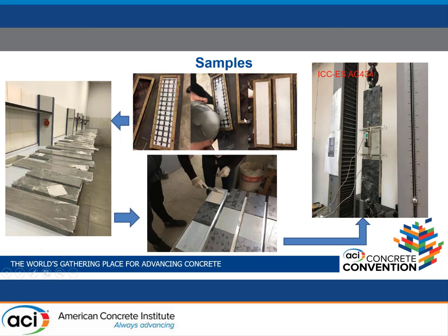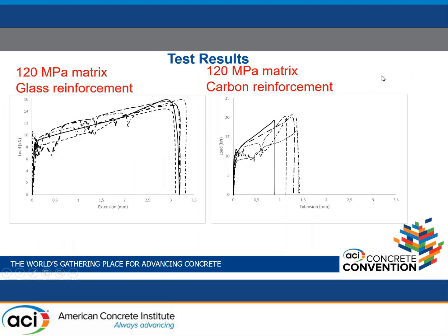This is the specimen preparation. We did apply first layer of the mortar, and then we put the fabric in the middle of the sample, and then second layer of the mortar was applied. Following the curing time in the sealing conditions, the metal plates were glued by means of epoxy resin. Then tensile tests were applied according to ICC-ES AC434 testing protocol. If we get to test results, composites produced with carbon fabrics showed significantly higher load values.